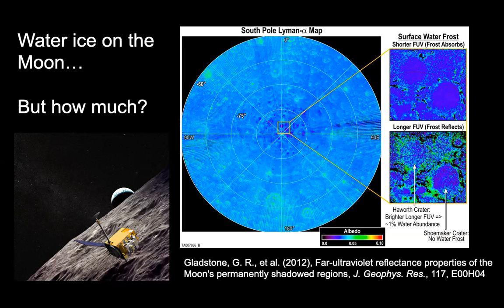The reason why that is stated as roughly is because there's actually not a lot of laboratory data to back up these quantifications of the amount of water that's associated with a certain amount of reflectance in the far UV. There was some work done during the mid-1970s, a paper by Wagner et al., focused on far ultraviolet reflectances. But since then, there's not been an awful lot of laboratory data to back this assertion up. So you could be talking about anywhere from 0.7% to 1.3%. It's a very rough measurement. And getting this exact is important for potential future in situ resource utilization applications. In other words, space missions, human space missions, being able to farm this water ice from these regions on the lunar surface to be able to use for rocket fuel, drinking water, etc.